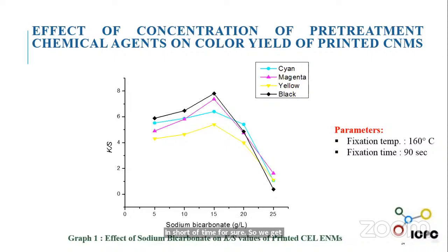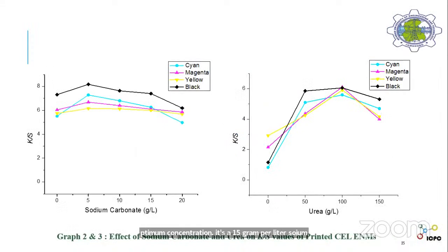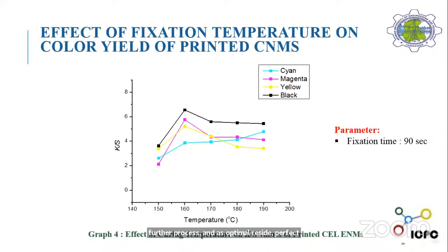So we get the optimum concentration at 15 gram per liter sodium bicarbonate, sodium carbonate at 5 gram per liter, and urea at 100 gram per liter. These are the concentrations of the chemicals we will use for the further process and as an optimal recipe for the pre-treatment process. Here is the effect of fixation temperature on the color yield of printed samples. We set different temperatures from 150 to 200 degrees, and we get the maximum color yield at 160 degrees Celsius.